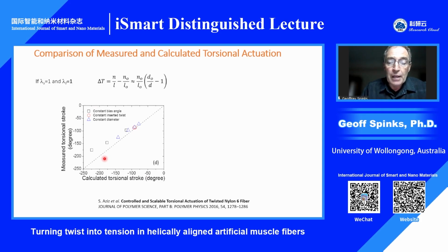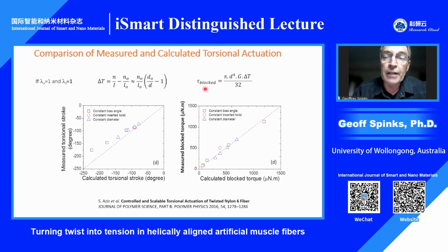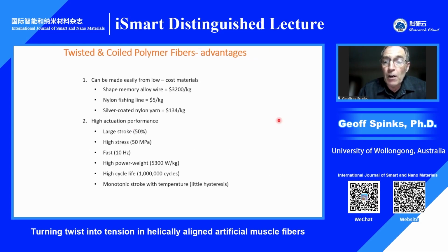Now, the other measurement we could make is to measure the torque generated, the blocked torque, by stopping any rotation and measuring how much torque's generated. And we could calculate the blocked torque as well from, again, our delta T equation, and then adding in the torsional stiffness components. And we then found that the measured blocked torque and the calculated blocked torque agreed really, really well. So again, the symbols are the measurements and the dashed line is the expected trend. So somewhat fortuitously perhaps, or in ways that we don't really fully understand, we can conclude that the single helix model works really quite well in predicting the torsional actuation for these twisted fibers.